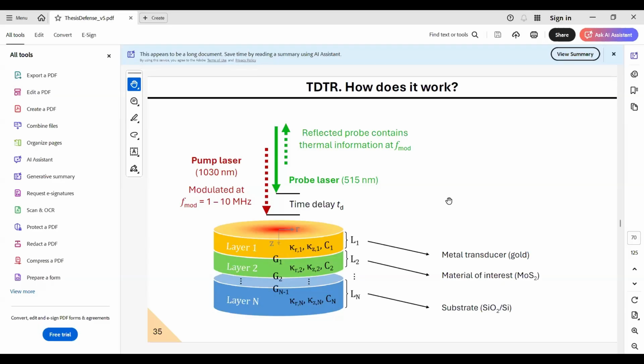I think you could. There are some experiments doing transducer-less TDTR. However, our films are so thin that if you illuminate them, you would heat up the entire z-axis. So therefore, you don't have a thermal gradient in the out-of-plane direction. And therefore, you would be mainly looking at in-plane transport and coupling into the substrate, I would say. So it would be very difficult to retrieve an out-of-plane thermal transport. So the transduction layer has to be opaque enough, let's say, but thin enough so you can still see the flakes. Yeah. Nice. See, I'm learning a lot.